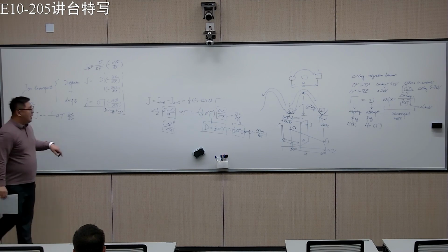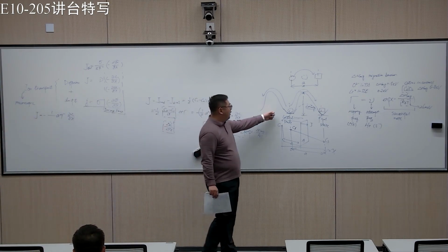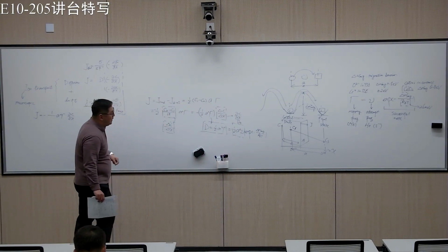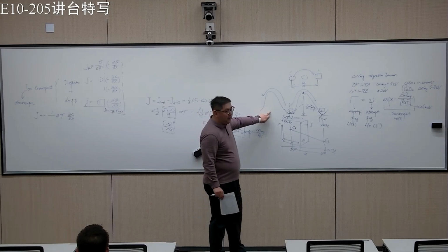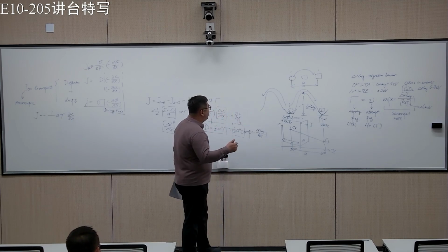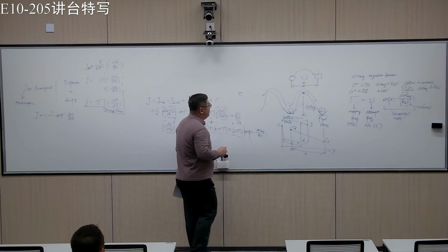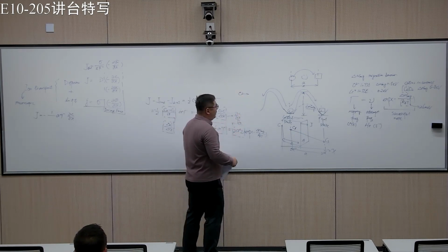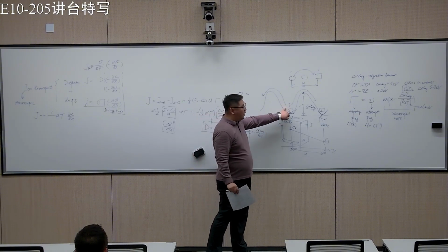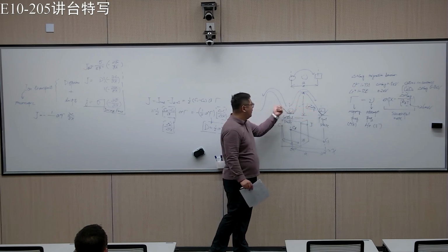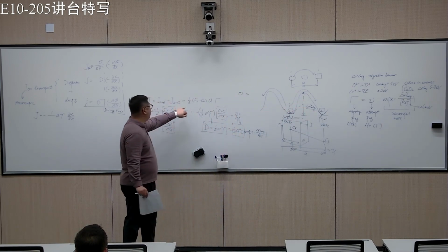However, remember that here we only imagine that it's one-dimensional. We know that in reality, it's not one-dimensional; we have three-dimensional structure for ionic crystals. Here we have the one half because ions can hop to this side or to the other side. So that's why we have one half here.